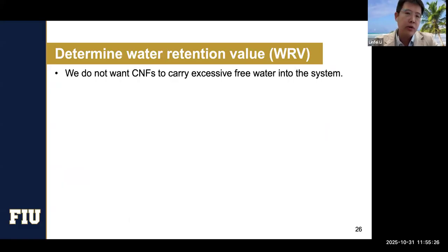But for internal curing purposes, I think the first challenge we're having is how we can determine the water retention value of that, because the CNF, well, we cannot ask it to carry excessive free water into the system. Otherwise, if you have excessive water in your system, you release it immediately and bring up the water to cement ratio, which is not good, right? Because we always want to keep the water cement ratio. So this is why we have to determine the SSD, the saturated surface dry condition, of the CNF. But it is really challenging.